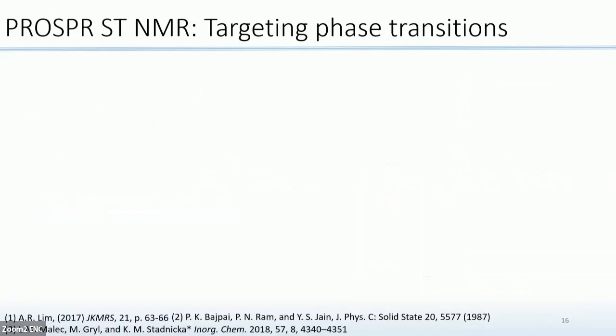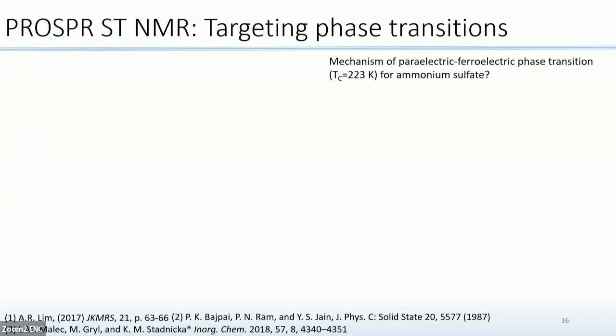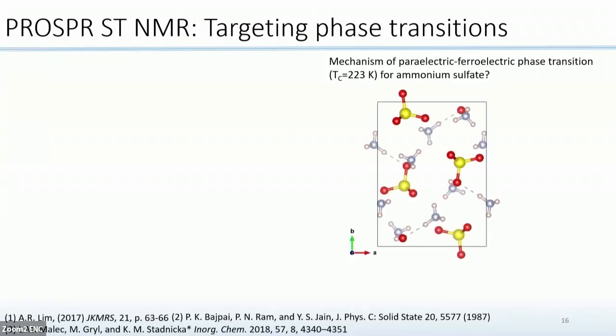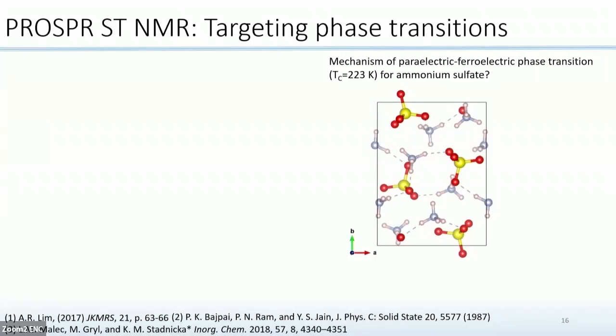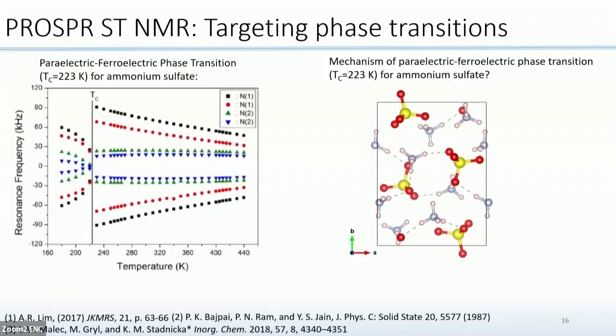So once we got these satellite measurements, we were wondering, what can we learn? Can we learn something new from it? It turns out that ammonium sulfate is quite an interesting material. It undergoes a phase transition at minus 50 Celsius or 223 Kelvin, and then it turns from paraelectric to ferroelectric. Ferroelectric is similar to ferromagnetic, except with electric polarization. There has been quite a long debate about the mechanism of this phase transition, whether it is the ammonium ion or the sulfate ion which is responsible.